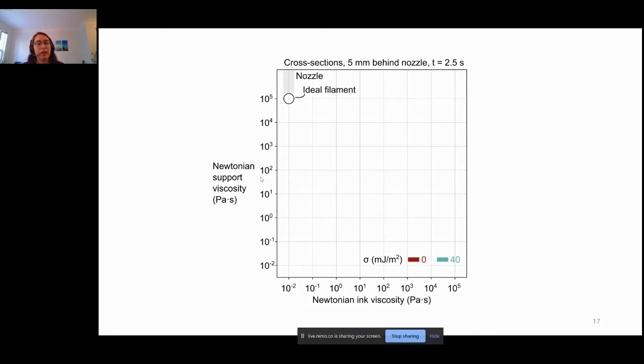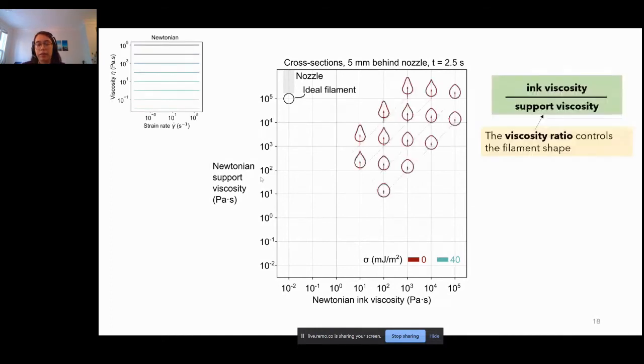We're also going to be looking at a circular shape because if there's any sort of sharp edges on these filaments, that could lead to porosity in the final part, or it could lead to surface roughness, both of which would be problematic. So for these Newtonian fluids, remember this viscosity is going to be constant with strain rate. And so here, what you can see is if you look down these diagonals, you can see that the cross-sectional shape is the same. So what that tells us is that the viscosity ratio is what's really controlling the filament shape here. So that's the ink viscosity divided by the support viscosity.